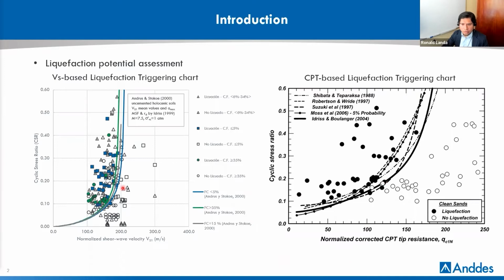On the charts on the screen, the CPT measures penetration resistance, so it's a large strain field test, while Vs measures the soil shear stiffness, which represents the soil response at very small strains. The cyclic liquefaction potential assessment is normally conducted under a cyclic stress approach, cyclic stress ratio, following the simplified procedure proposed by Seed and Idriss almost 50 years ago. While calculating the cyclic resistance ratio of leach ore, most of us have found that while using Vs and the CPT-based approaches, some differences are obtained in their respective estimates.